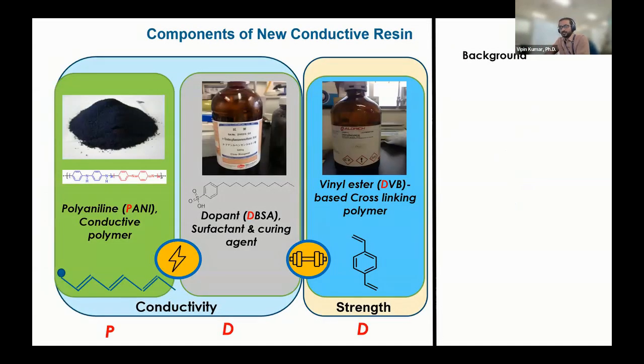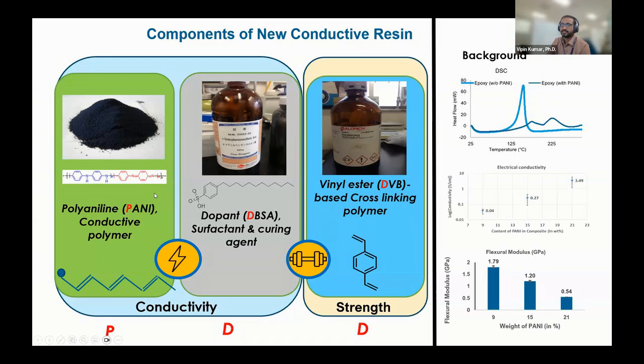So this goes a little bit into chemistry, but I'll try to keep it simple. You have 3 components in this resin system, where the polyaniline has alternating single and double bonds, and when you dope this polyaniline with a strong acid, let's say a sulfonic acid, you allow the charge to jump from one end to the other end, creating the electrical conductivity in your polymer chain. On the other hand, the strength comes from the thermosetting resin called DVB, which is a vinyl ester-based resin system. And again, the data says the more conductivity you want, the more strength you lose. So I can improve the conductivity a lot by having more of this portion, but then I lose the mechanical properties. It's a give and take scenario.